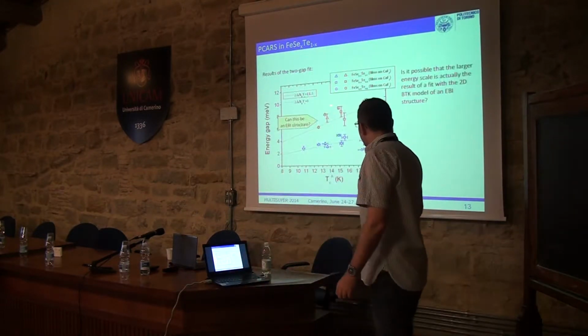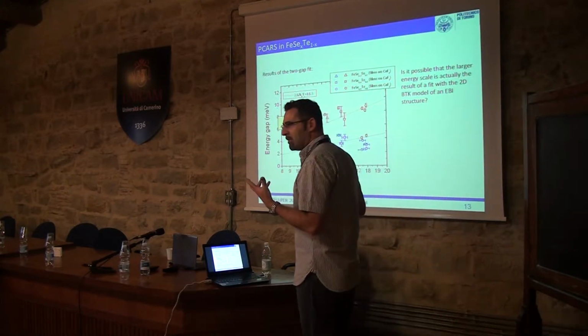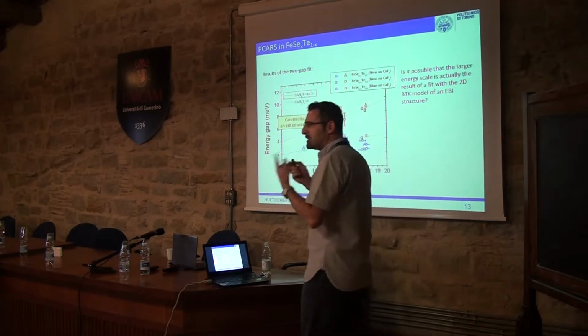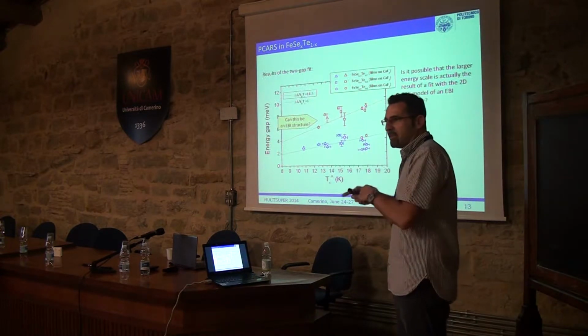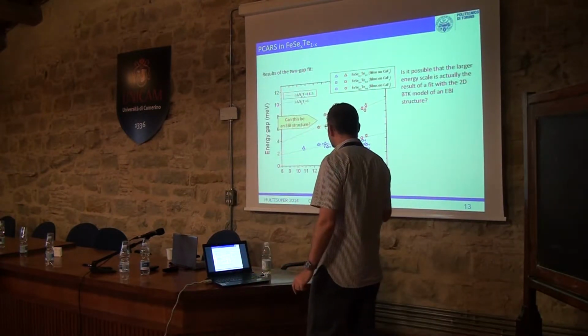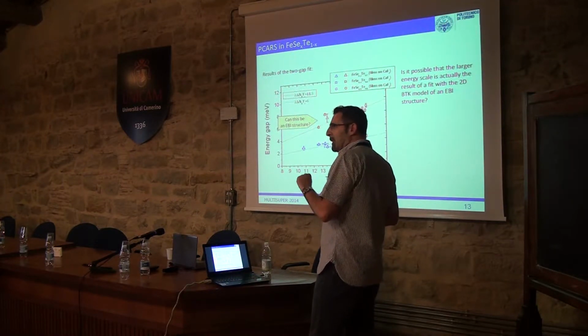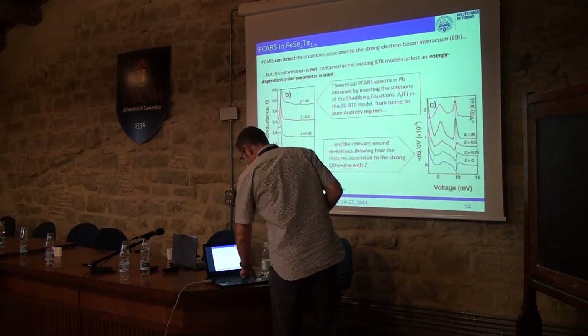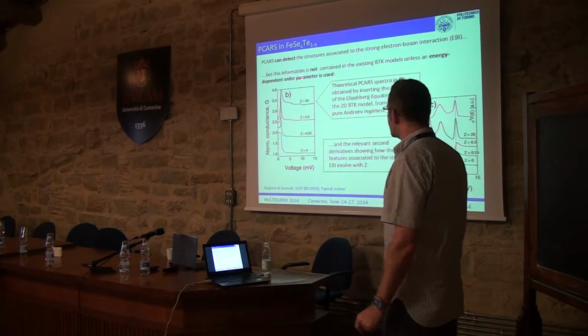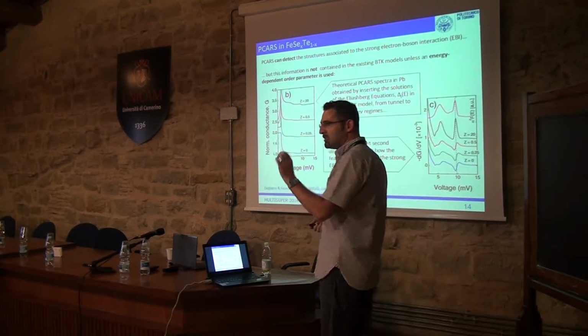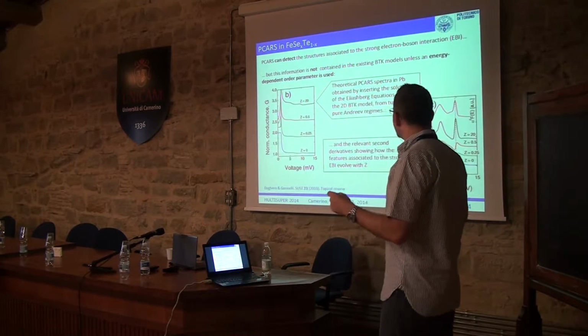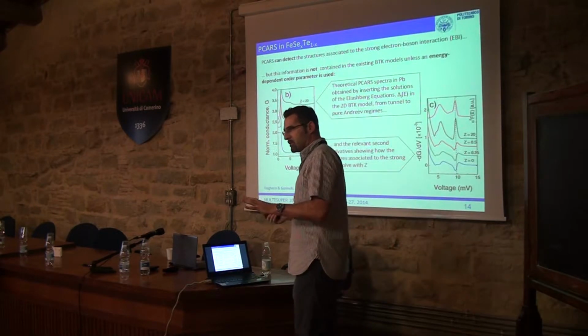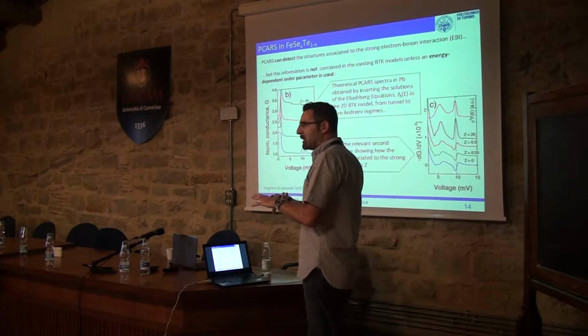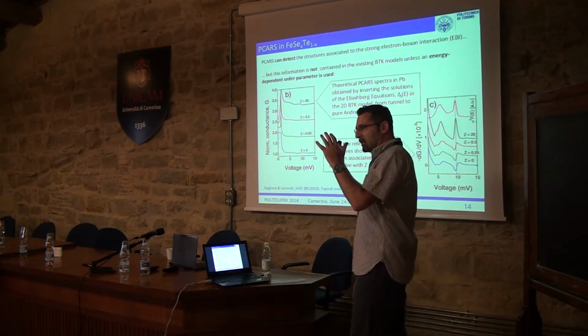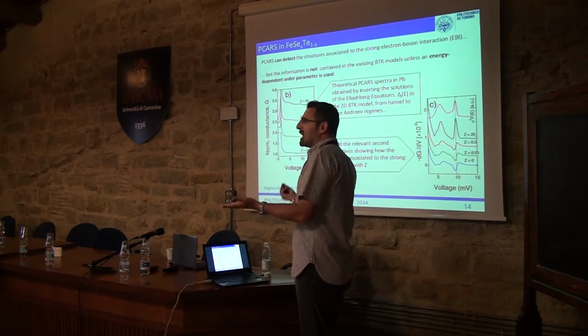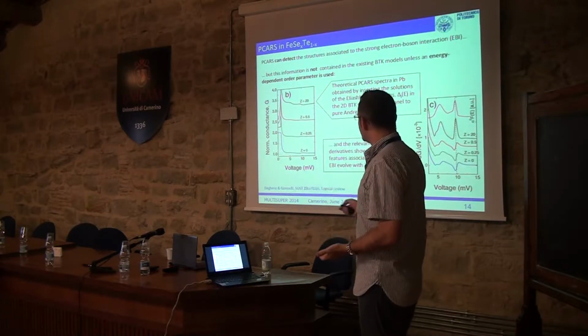So we were wondering, can this be something which is not a gap? Maybe these additional shoulders are not gaps, but we are mistaking them for gaps and fitting them even though they are not gaps. To check whether these values are actually due to the fit of electron-boson interaction structures, we performed some calculations within the Eliashberg model. Why Eliashberg? Because point contact can detect the structures associated with strong electron-boson, electron-phonon, whatever interaction, but the BTK models do not contain this information. So to be able to see, reproduce and analyze these structures, one needs to calculate the energy-dependent gaps from Eliashberg, and put these energy-dependent gaps in the BTK model. In such a way, the BTK model reproduces these features.